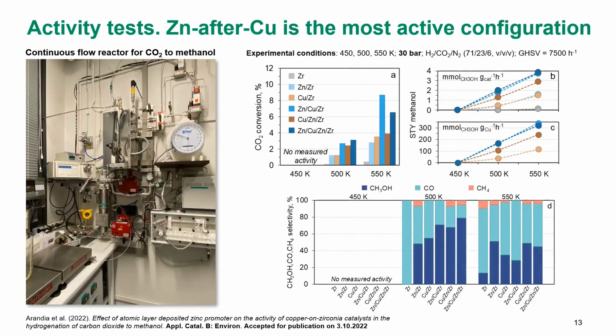Yes, sorry for the amount of results here, but what I plot here is the CO2 conversion for three different temperatures, the methanol production expressed as millimoles of methanol per gram of catalyst per hour, and the same thing per gram of copper, and the different selectivities. In our case, we detected methanol, carbon monoxide, and methane. But what I want to tell you is that if we look at the CO2 conversions, again, we see that the catalyst where the zinc was added after copper, the conversion was higher at 500 and 550. You see a real difference here.